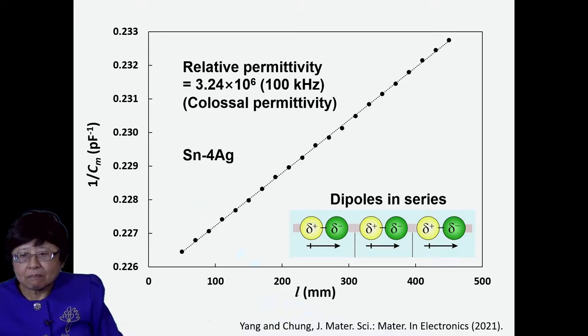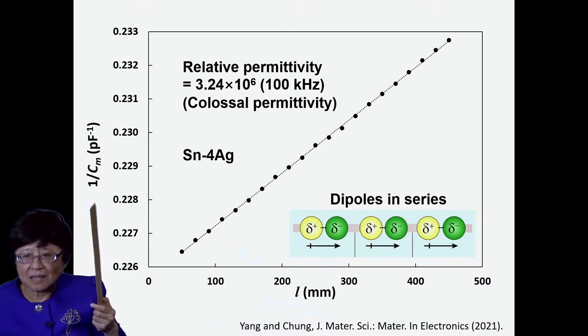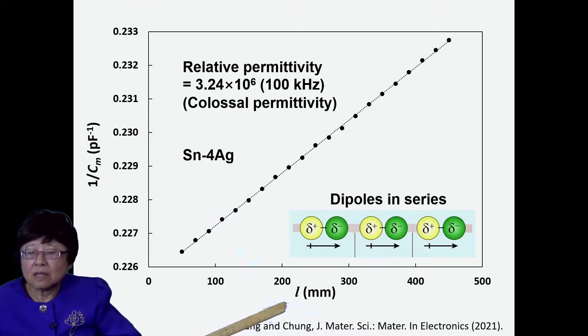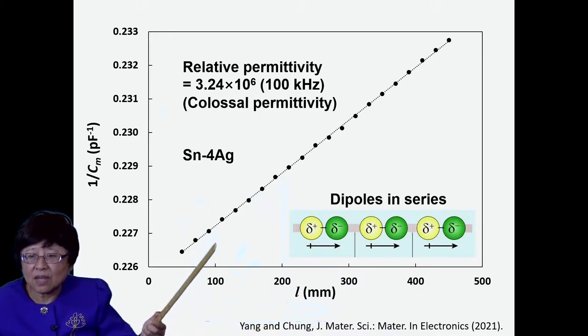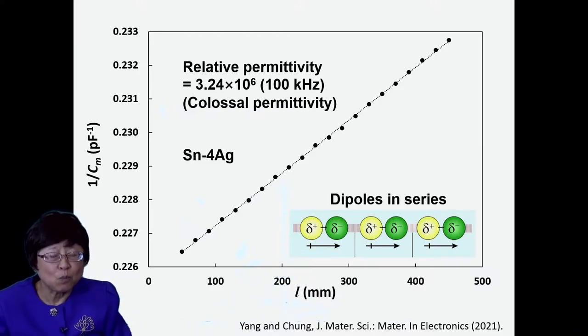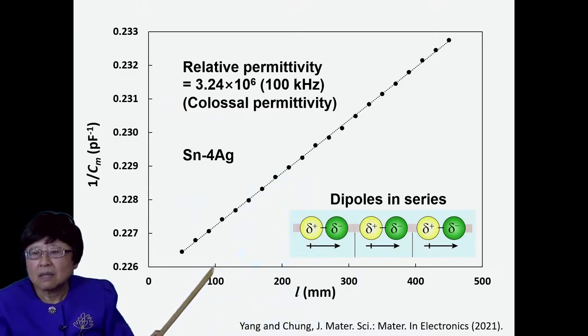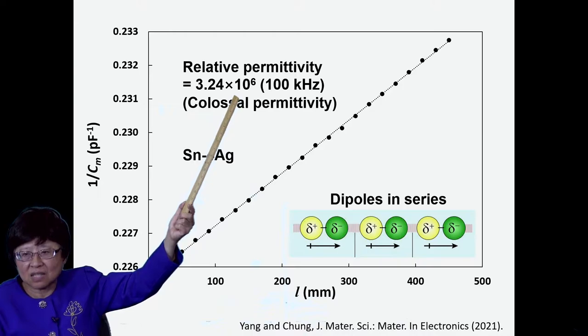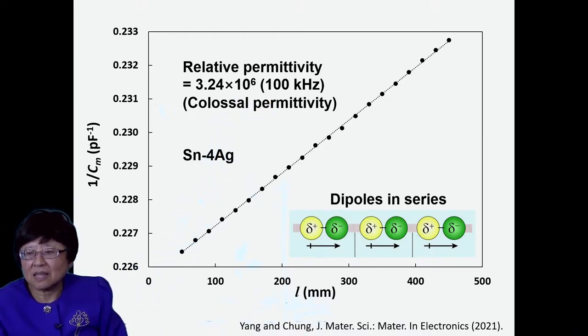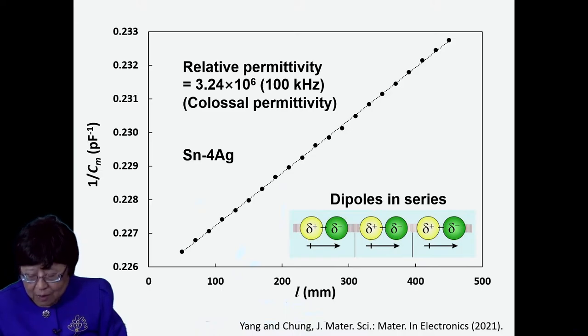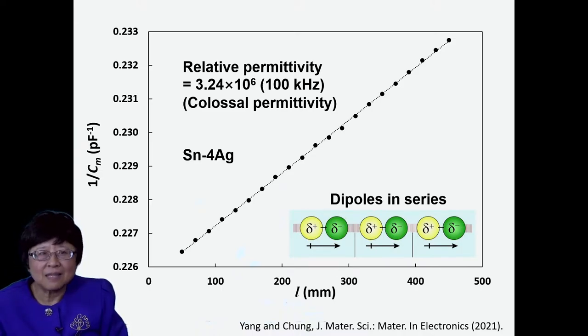Now the permittivity is associated with capacitance, as I said, and one can measure the capacitance. And if one plots 1 over the measured capacitance versus the inter-electrode distance used in the capacitance measurement, one gets a straight line like this. And this indicates dipoles in series, because dipoles in series involves 1 over C. And from the slope of this plot, one gets the relative permittivity, which is around 10 to the 6 at 100 kilohertz in this case. And this material is tin-4-silver solder. So indeed, the relative permittivity is very high for conductors, as predicted by Jonscher back in 1999.